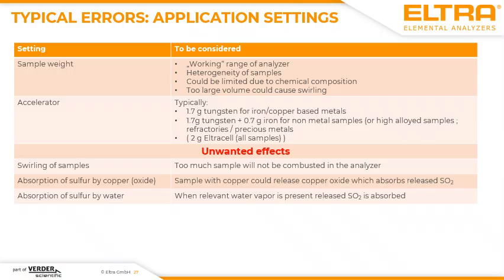Then, after the correct sample weight, you have to think about the accelerator. Typically, for powder-based samples, you can just apply 1.7 gram of tungsten, which is usually 1 spoon, for an iron-based sample. This is quite a typical application, and then you are on the safe side for analysis. When the sample is, for example, ceramic based, then you can apply 1.7 gram of tungsten and 0.7 gram of iron. This is also a typical application for non-iron-based samples to get reliable results.